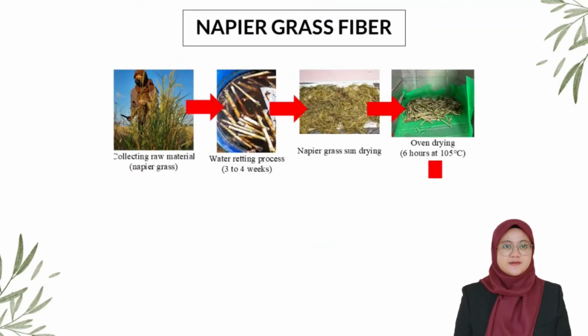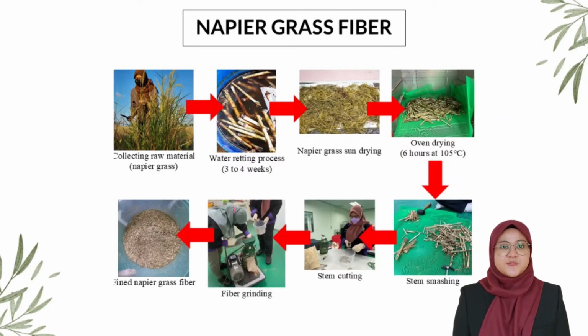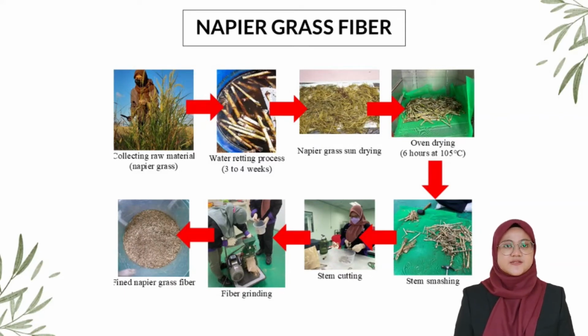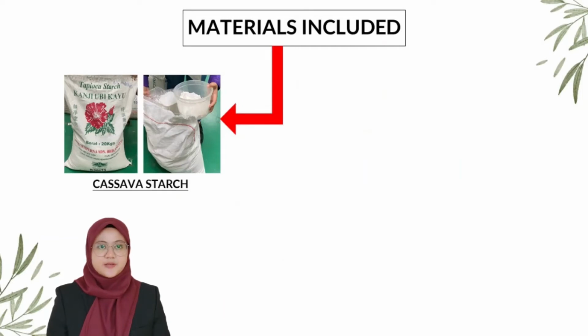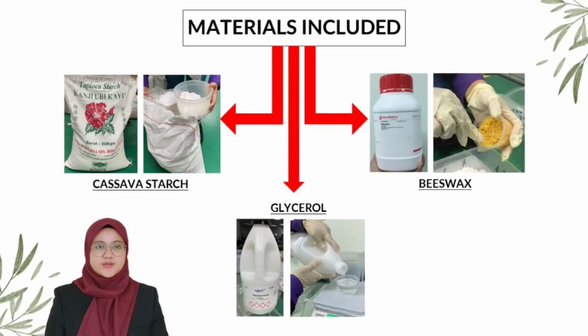Next, this was the procedure done for extracting the Napier grass fiber. Firstly, the raw material for this study, which is Napier grass, was collected. Then, the stems collected underwent a water retting process for 3 to 4 weeks. After that, they were dried under direct sunlight. For maximum drying, the Napier stems were dried in the oven for 6 hours at 105 degrees Celsius. The stems were then smashed and cut into small pieces before grinding to obtain the fine Napier grass fiber. Other than Napier grass fiber, the materials used in this study are cassava starch, glycerol, and beeswax.